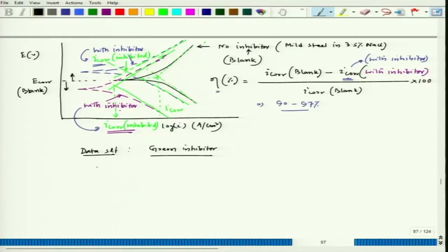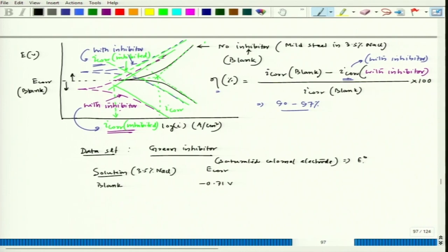Now, one such example is, when we talk about blank, there we are simply using, or we can say, solution. And the solution is 3.5% NaCl, and there we are adding inhibitor. Now, in one case it is blank, and then we can find out E corr. So, when it is blank, it's minus 0.71 volt. And this is with reference to the saturated calomel electrode. So this is the reference electrode that we use, where E naught with respect to the standard hydrogen electrode is plus 0.241 volt. That steel, and here we are using mild steel, low carbon nominal composition mild steel.